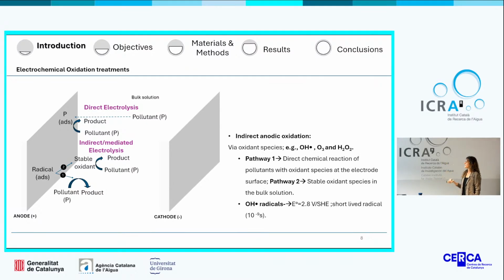On the other hand, there is indirect anodic oxidation via different oxidant species, as for example, hydroxyl radicals, ozone, or peroxide. This indirect anodic oxidation can be performed in two different pathways: when the oxidant species is stable in the bulk solution, or when this oxidant species is adsorbed onto the surface. From all these mentioned oxidant species, the most powerful one is the hydroxyl radical, because of its high oxidation potential.